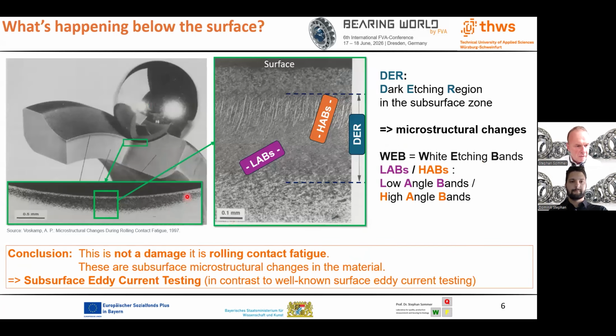So what's happening under the surface? You see an inner ring of a ball bearing, and the ball. And in the contact area, you see under the surface this dark etching region. This is this region here. And if we zoom in, this is the surface. This is then the unaffected part of the surface. And here starts the dark etching region. And in this dark etching region, there are white etching bands, high angle bands and low angle bands.